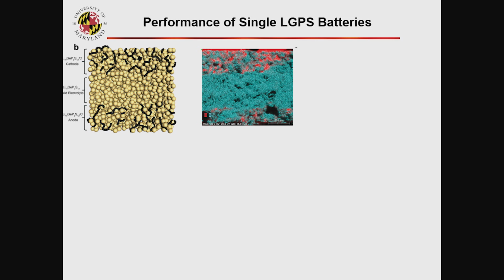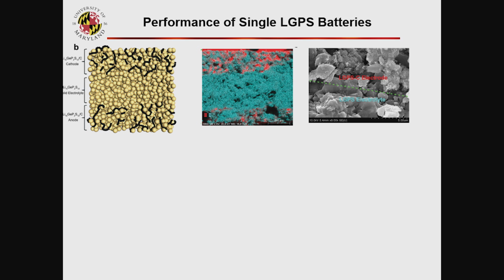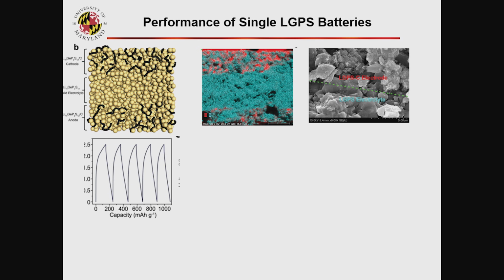The reason is the germanium sulfide, they have a conversion reaction. The conversion reaction is not reversible. We have a more lithium sulfide cathode to compensate on the conversion reaction irreversible capacity. The alloy reaction is totally reversible. So this is simple SEM. Here we have carbon, here no carbon. Just press. And then we get a charge discharge curve.